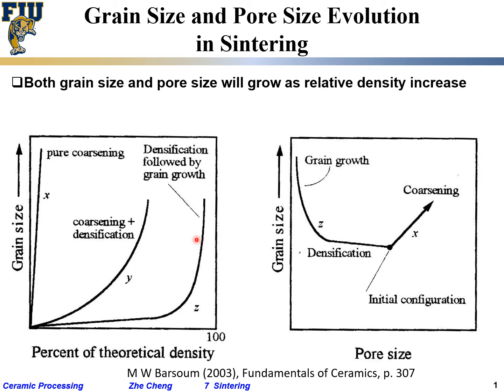The middle case is somewhere in between — during sintering you have a combination of grain growth and densification simultaneously. The message is: you try to avoid pure coarsening, get as close as possible to the ideal case. But towards the very end, even for flash sintering or SPS, within a few minutes or even a few seconds the grain growth goes up dramatically.